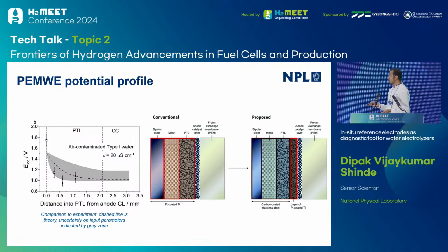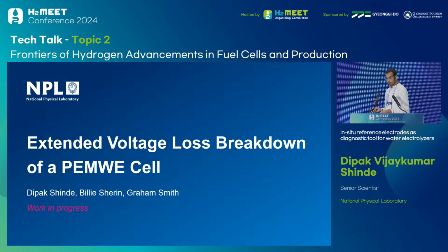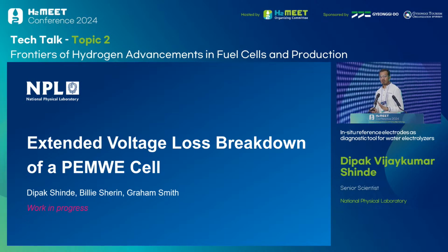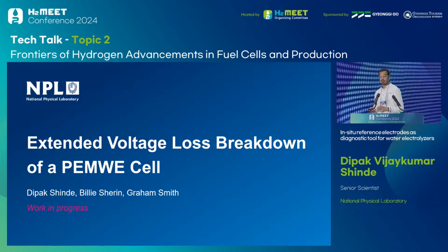And based on these results, we propose a new kind of device architecture for PEM electrolyzers. So this is a conventional design. Instead of this, we propose to replace part of the PTL, the mesh and the bipolar plate with carbon coated stainless steel instead of platinum coated titanium, which is shown here. So you need only a very thin layer of platinum coated titanium near the anode catalyst layer, where it experiences the corrosive potential. But after that, you can get away with materials such as carbon coated stainless steel. Now, this was about CAPEX and how you can lower the cost of your PEM electrolyzer.